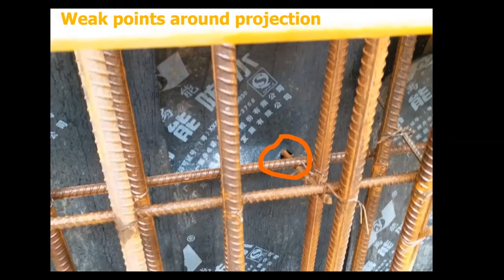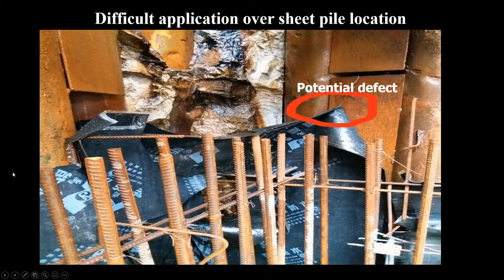So the big problem with membranes, for a start, if we look at this particular detail, you've got starter bars coming out of the piling behind that membrane connected to the reinforcement. There's no way in the world that you can actually seal that properly and stop water getting through. Wherever you've got a surface penetration, you've got a potential problem with membrane waterproofing. Some other horror stories here, you've got trying to dress a membrane over the top of some very jagged rock and it's very difficult to apply. Essentially, it's riddled with defects.